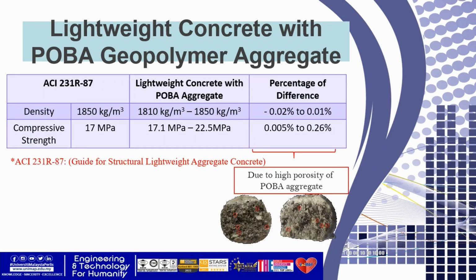And here is the comparison of the lightweight concrete with POBA geopolymer aggregates against the American Concrete Institute guide for structural lightweight aggregate concrete. As we can see here, the density is almost similar, and the compressive strength of the lightweight concrete with the POBA geopolymer aggregate is higher than the ACI provided.